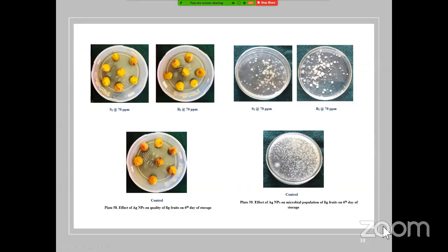And this is part of my work. I have dipped the fig fruits in silver nanoparticle solution, and it extends the shelf life of figs for about 6 days. These are standard silver nanoparticles. These are biologically synthesized silver nanoparticles, and this is the control. And these are the different microbial populations on the 6th day of storage. And here we can see that the biologically synthesized particles are on par with the standard particles. So we can use biosynthesized silver nanoparticles for nano coating.